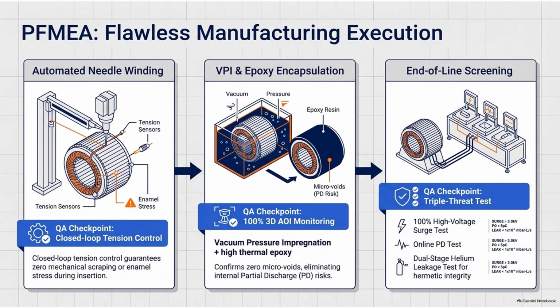And once the physical winding is complete, it has to be locked into place to prevent the vibration damage we discussed earlier. It goes through vacuum pressure impregnation, or VPI, followed by epoxy encapsulation. Walk me through the physics of VPI. Why not just dip it in epoxy and let it dry? Because dipping leaves air. In VPI, the entire stator assembly is placed into a chamber, and a massive vacuum is pulled, sucking every molecule of air out from inside the microscopic crevices between the tightly wound wires. Then, highly thermally conductive epoxy resin is flooded into the chamber, and the pressure is reversed, driving the resin deep into the windings via capillary action.